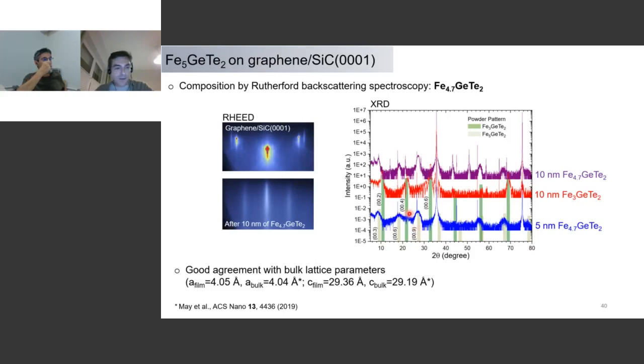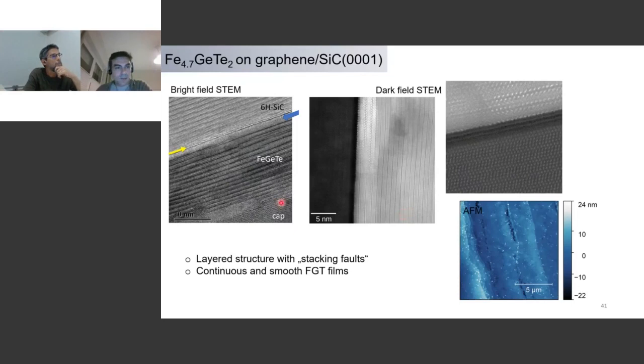So finally, another 2 minutes, and then I show you here, we want to increase this Curie temperature even more for this FGT ferromagnetic material. And as I told you in the beginning, one of the ways of doing that is stuffing more iron within these layers. And that's what we did. We grew this iron 5 germanium telluride, and we get by XRD the information that we are growing the right layered phase with more iron stuffed in between. And that's what we get here, some TEM, which proves that we do have a layered film of FGT that is growing on top of silicon carbide.